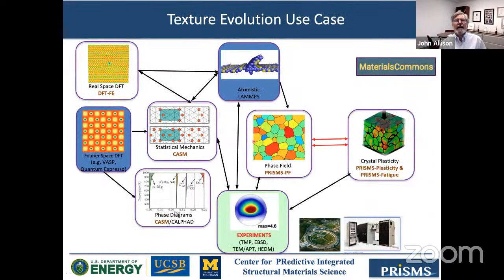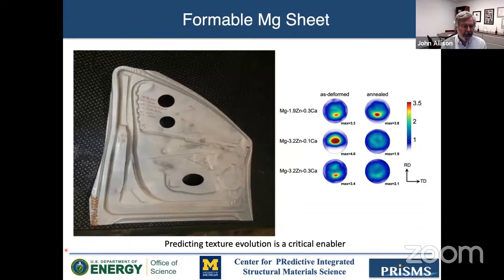So let's see. Okay, so I've got a couple of little segments I want to talk about here still. So texture evolution. So this is a new thing for us, and here we're combining all of the tools to predict texture evolution in these magnesium alloys. And this is particularly important for sheet formability. So magnesium alloys are very difficult to form at any kind of reasonable temperatures and strain rates. And so formable mag alloys, these rare earth alloys are formable, some of them, and that's because they have this softer texture. And we had the opportunity to work with USAMP to work with some of these alloys.